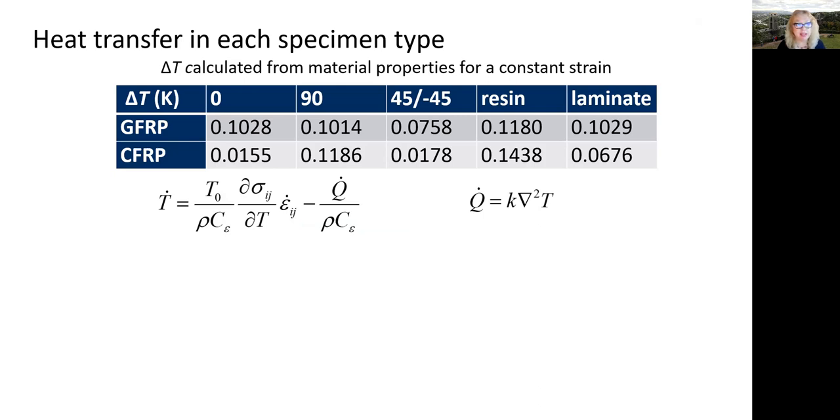If we increase the rate of change of strain by increasing the cyclic loading frequency, the left-hand term becomes larger and therefore any heat transfer that's occurring reduces.